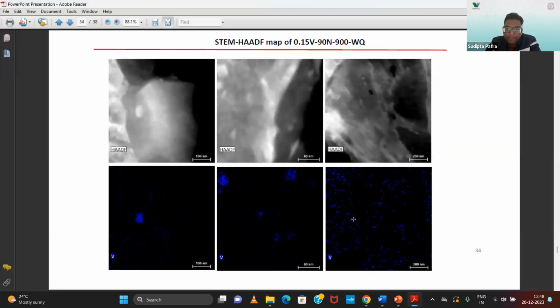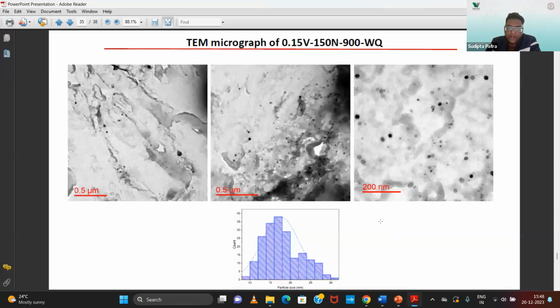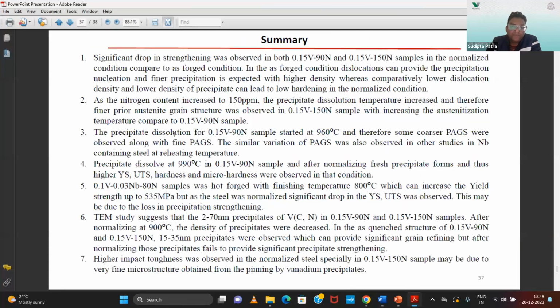So these are the STEM elemental maps. You can see the very fine vanadium distribution here. And the unique point of 150 nitrogen is that at 900 degrees centigrade you could also see very fine precipitates. They are stable at that temperature and are present to refine the grains. So with this we can conclude that vanadium and nitrogen can effectively increase the precipitation strengthening to a very high level in the as forged condition and as rolled condition, as well as the normalized condition.